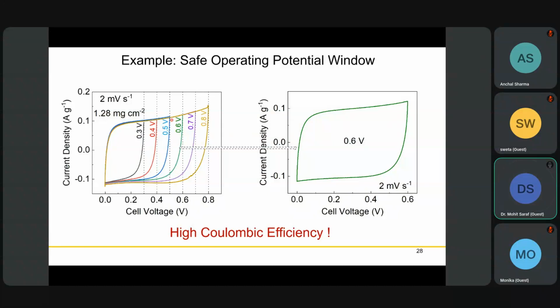But let's say in 0.7 volt, you start losing your Coulombic efficiency. Discharging area becomes more than charging area, and you get Coulombic efficiency somewhere around 110%. That means there is some problem, some kind of side reaction, so I will stop there. Maybe I can go up to 0.65 volt also, but for this particular case, I found out that 0.6 volt was giving me a very good Coulombic efficiency. So that should be my